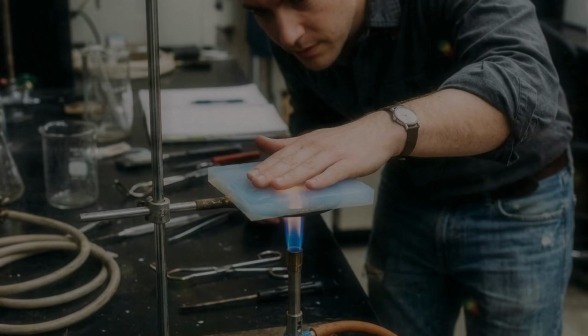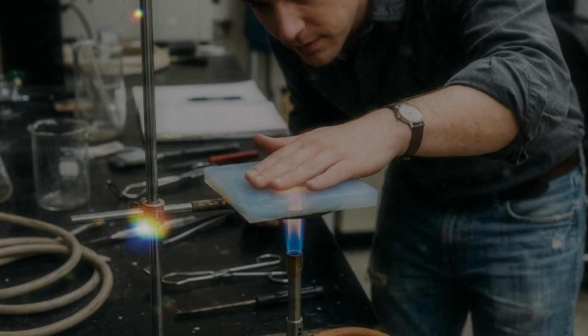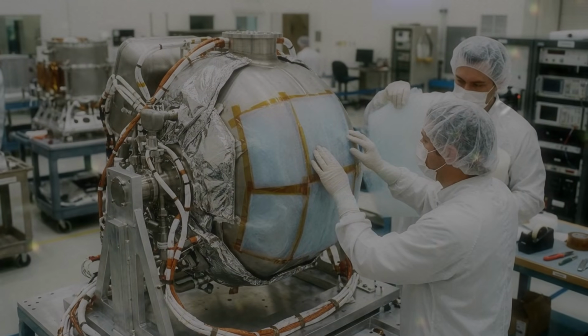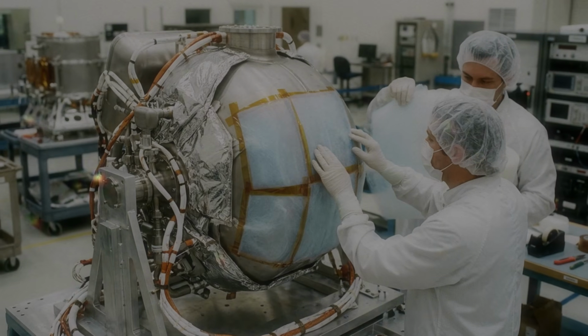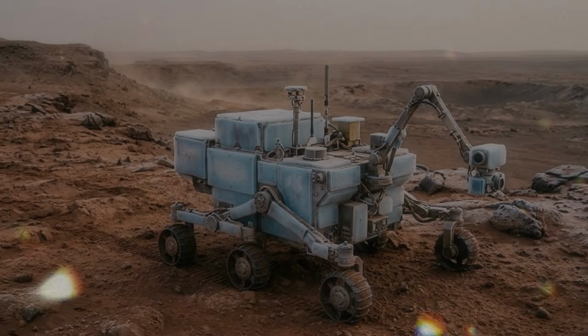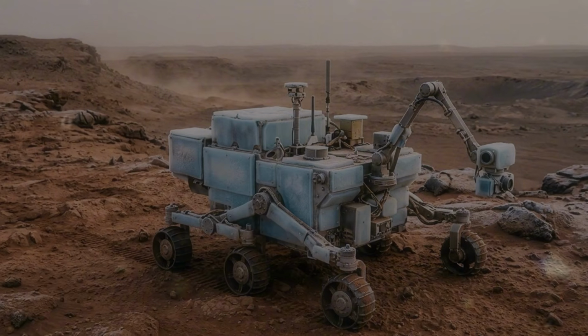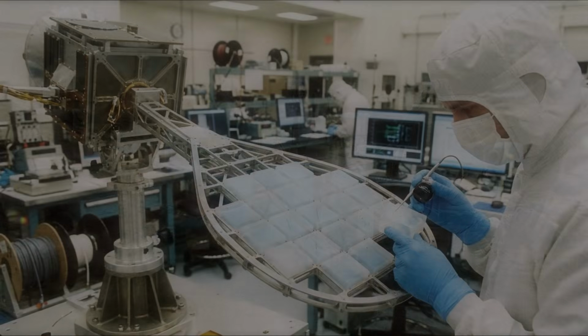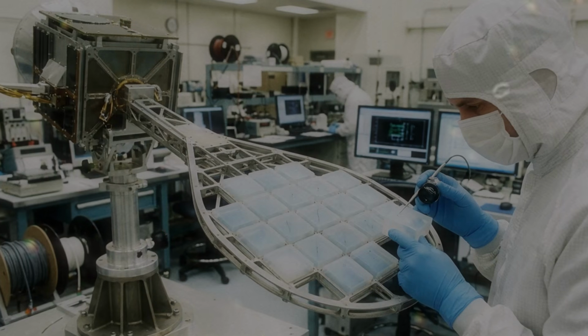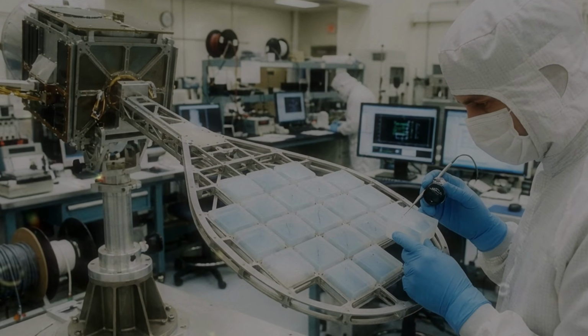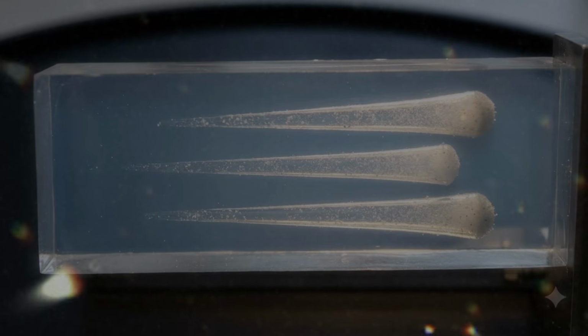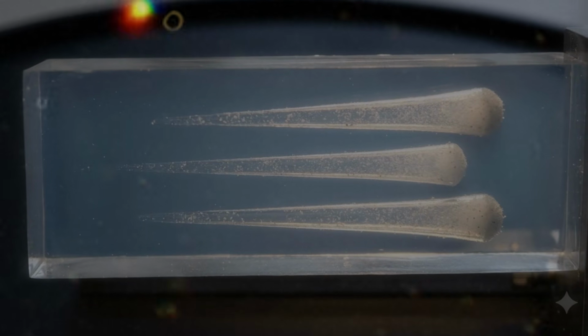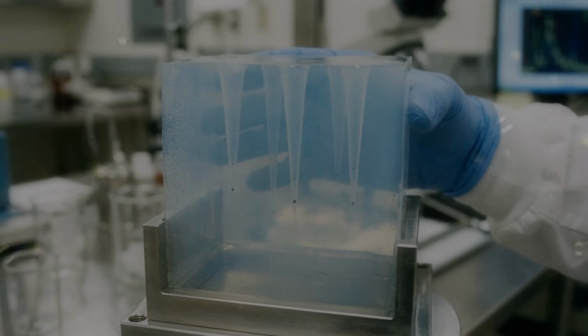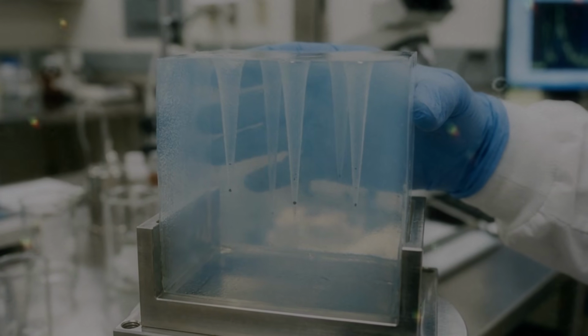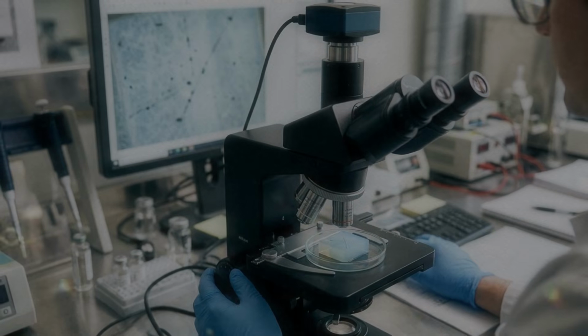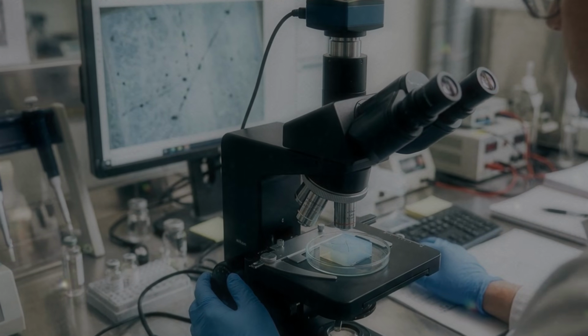For traditional silica aerogel, drying remains one of the largest obstacles. Supercritical drying can preserve a very fine pore structure, but it requires pressurized equipment and careful control. Future production is likely to rely increasingly on methods that work at ordinary pressure, use safer liquids, shorten the number of washing steps, or allow solvents to be recovered and reused. Ordinary pressure drying is already possible for some aerogels. The challenge is reducing shrinkage and cracking while keeping the material light. Scientists can strengthen the gel before drying, change the chemistry of its surface, or choose liquids that pull less strongly on the pores as they evaporate.